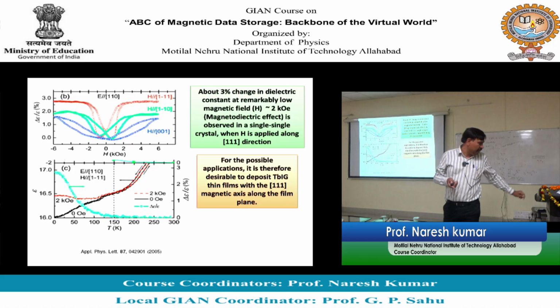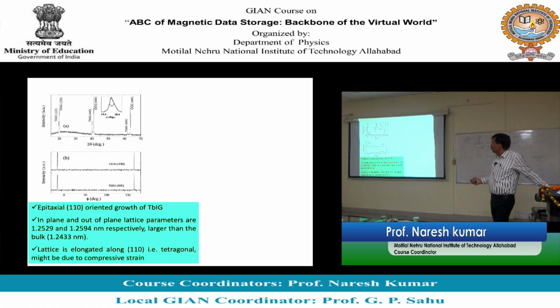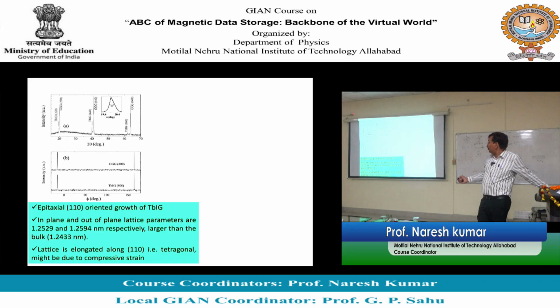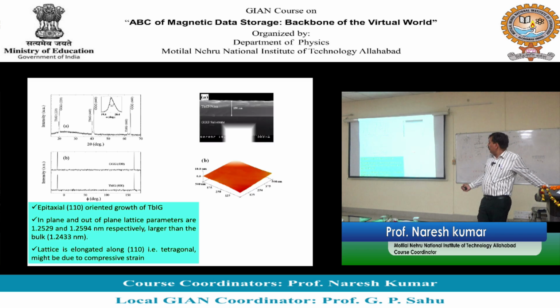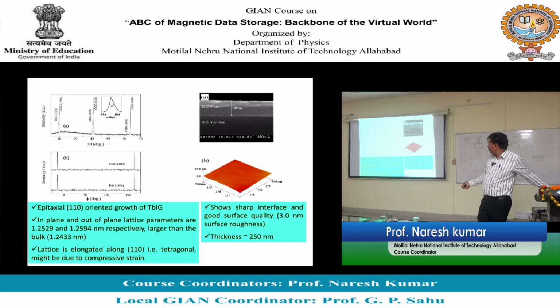This was selected that way, and yes, we could grow these films, highly epitaxial films. For epitaxial growth, we had to select a substrate of similar crystal structure. So we used GGG, which is gadolinium gallium garnet with the same structure, and the orientation we opted was 220. So we could grow these films epitaxially, highly epitaxial films. There was absolutely no other orientation present.